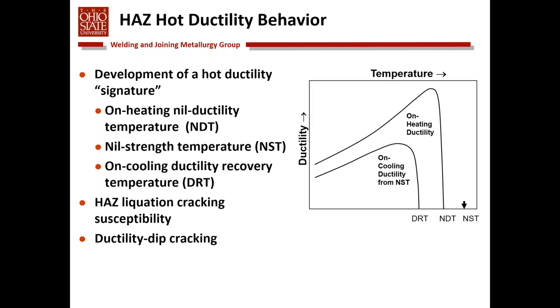A very common test, and probably one of the oldest tests developed using the Gleeble, is something called the hot ductility test. What the hot ductility test does is determine the ductility of the material both on heating and on cooling from some peak temperature. So the chart here to the right basically shows typical data that you might get. The data of interest to us with respect to cracking susceptibility is what's called the nil ductility temperature, or the zero ductility temperature on heating.